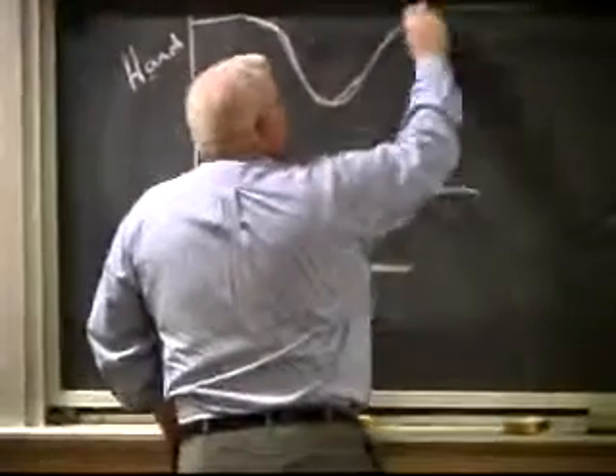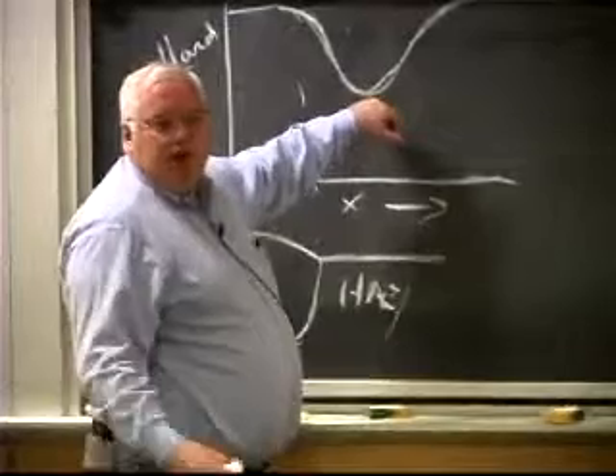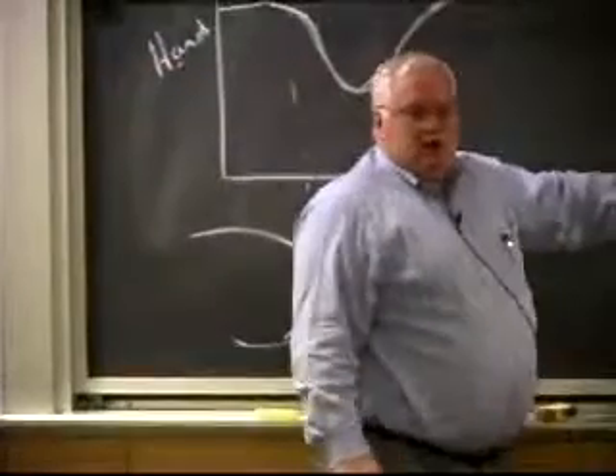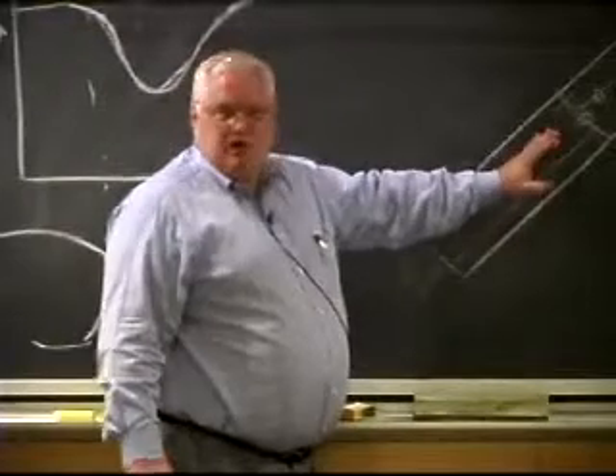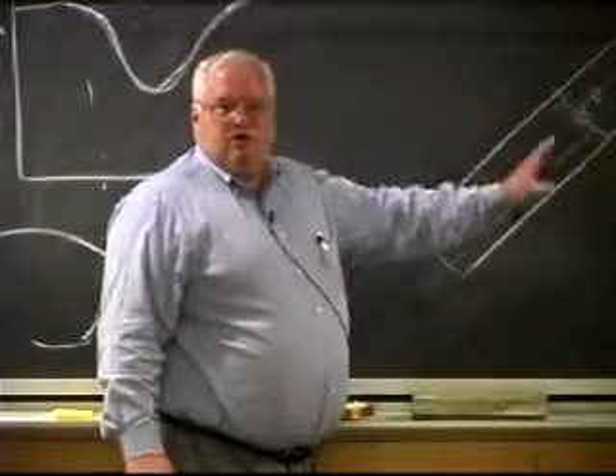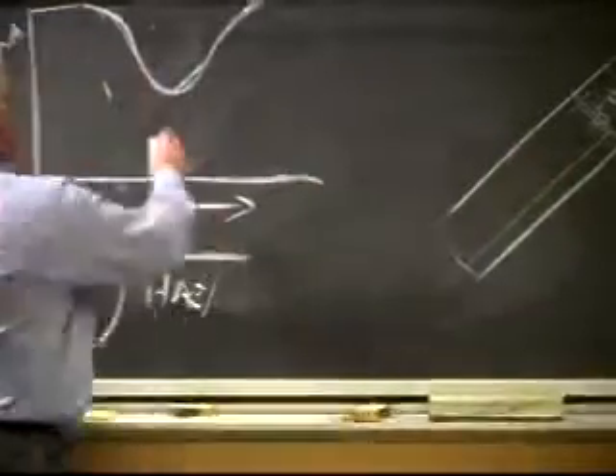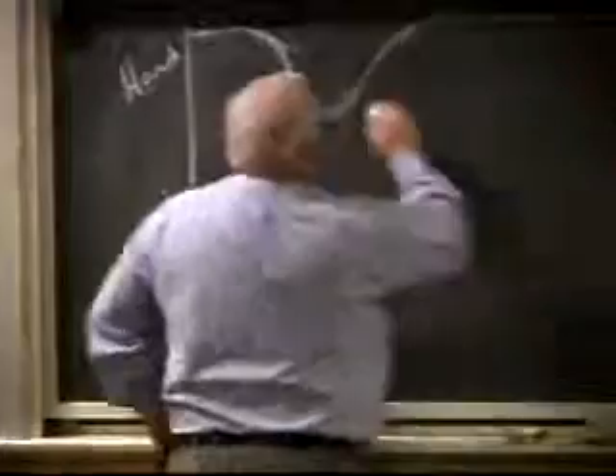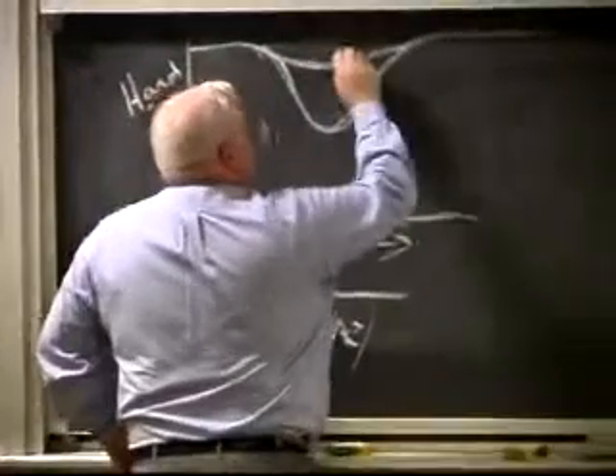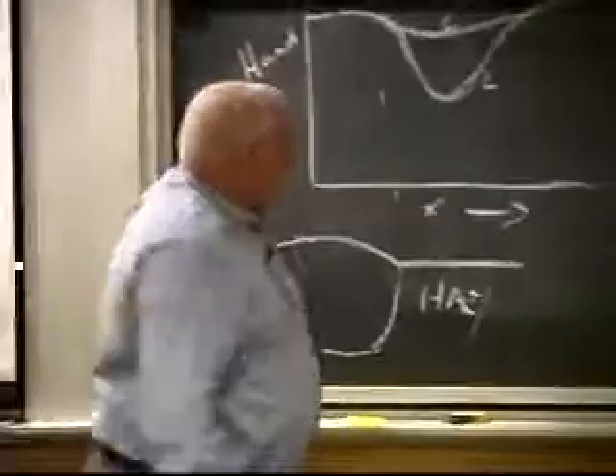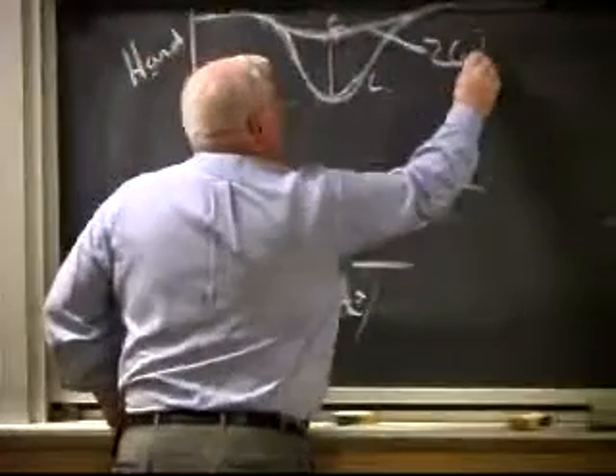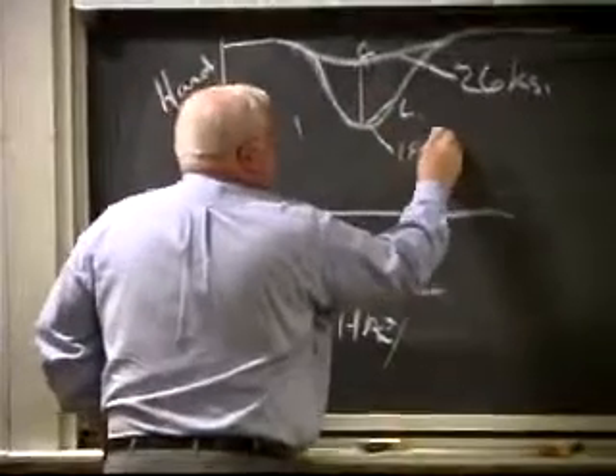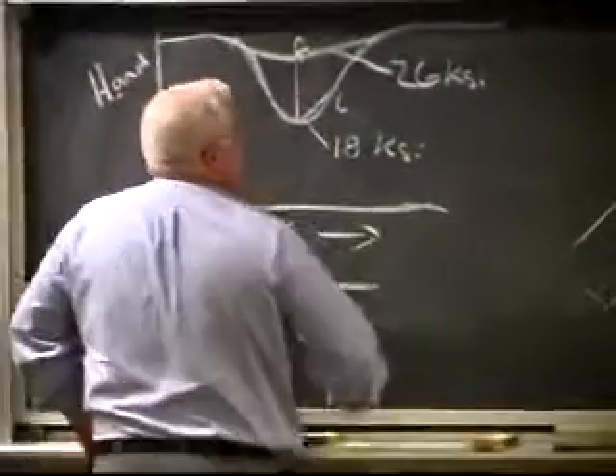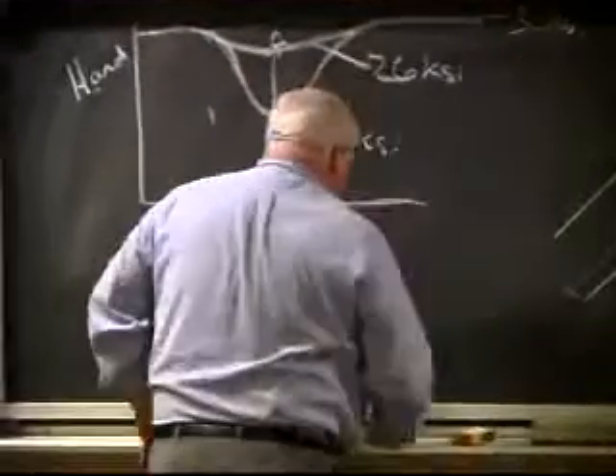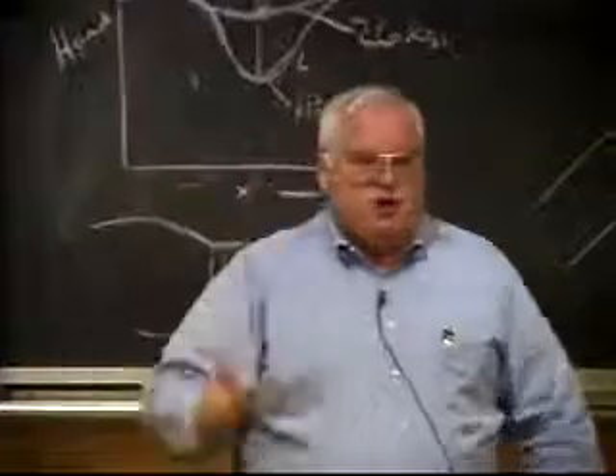If you looked at the hardness of the longitudinal weld, which had never yielded, never seen stresses in service, plus you have to recognize, no one really quite knew when they designed this, and even 15 years ago, what the effect of a hurricane coming through here was in terms of what the real stresses were on this. But the circumferential weld had a profile like that. And from that, I was able to tell them, if I remember, that the hardness was equivalent to 26 KSI. This was like 18 KSI down here, and the strength of the material was supposed to be like 30 KSI. I was able to tell them that over the previous 25 years, the maximum stress that thing had ever seen was 26 KSI, because I had work hardened it to 26 KSI.